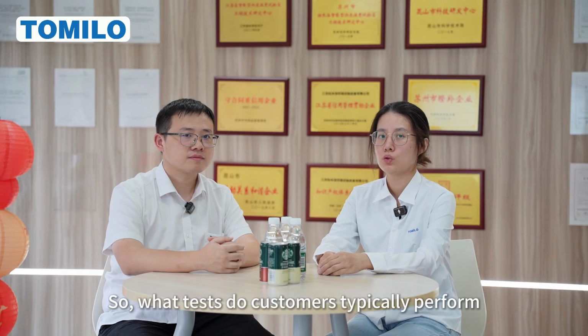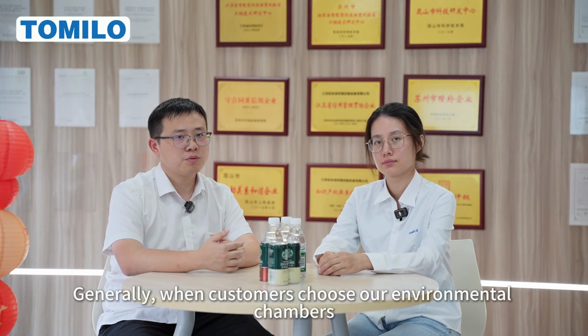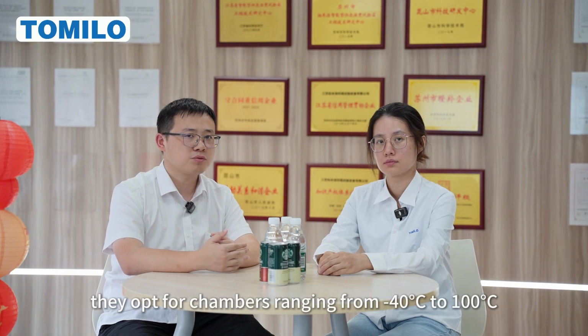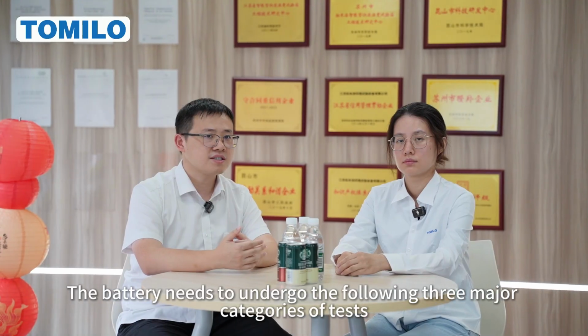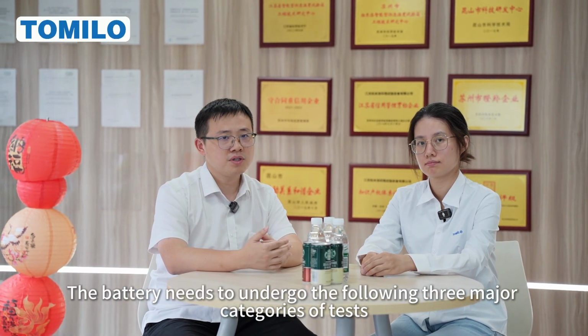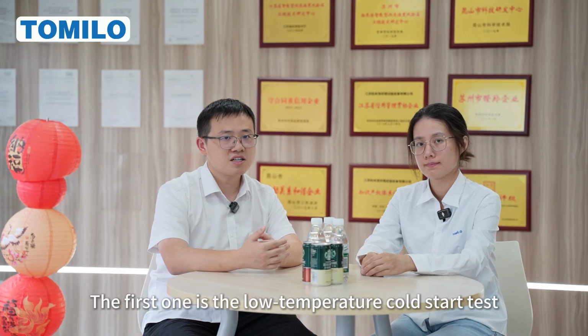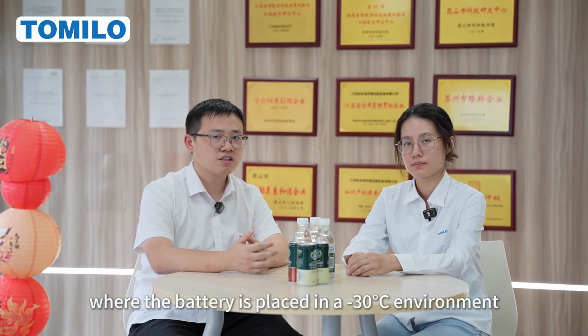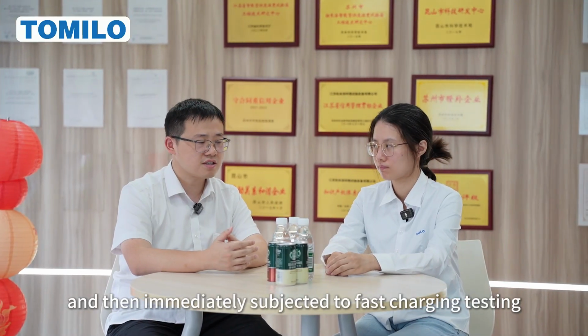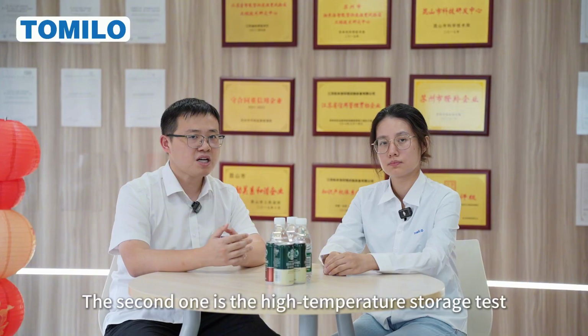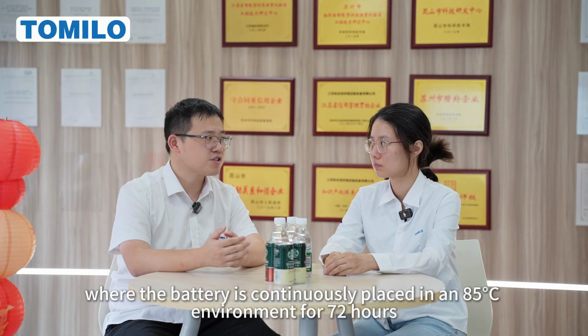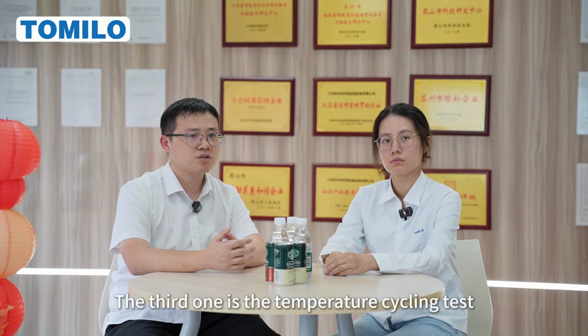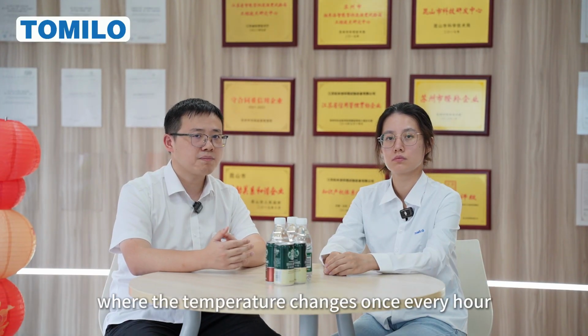So, what tests do customers typically perform using our environmental chambers? Generally, when customers choose our environmental chambers, they opt for chambers ranging from -40 degrees Celsius to 100 degrees Celsius. The battery needs to undergo the following 3 major categories of tests. The first one is the low-temperature cold start test, where the battery is placed in a -30 degrees Celsius environment for 12 hours, and then immediately subjected to fast charging testing. The second one is the high-temperature storage test, where the battery is continuously placed in an 85 degrees Celsius environment for 72 hours. The third one is the temperature cycling test, where the temperature changes once every hour in an environment ranging from -40 degrees Celsius to 85 degrees Celsius for a total of 10 cycles.